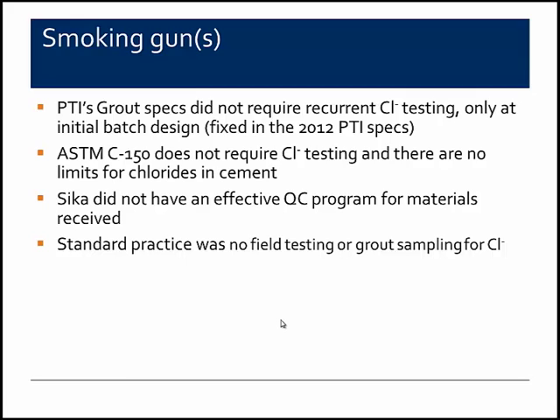It also was apparent to those of us in the industry that Sika and possibly other grout suppliers may not have had an effective QC program for their materials received processes. And I do understand that those grout producers now are aware of this issue and are testing their received products, the constituents that they use to produce the grout. And then in addition to that, the standard practice for many DOTs was that they weren't doing chloride testing in the field. They were taking manufacturer certifications that it contained no chlorides as good enough. And so that practice has also changed in recent times.